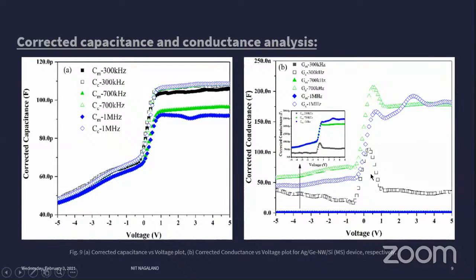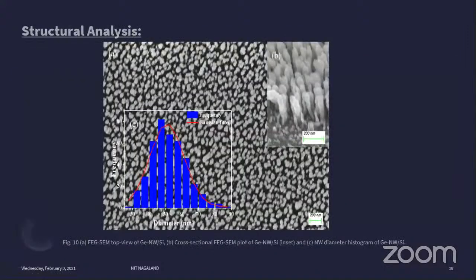This is due to the presence of charge transfer at the interface, and this is the structural image wherein we found that the height is around 152 nanometers and the width around 52 nanometers. The Gaussian plot agrees with our estimated diameters.